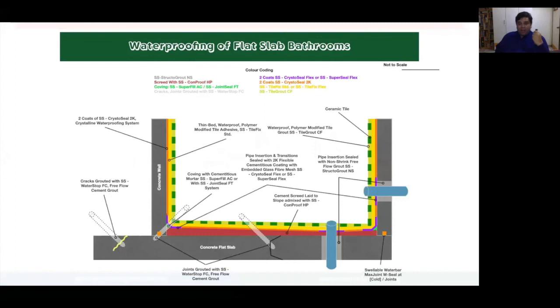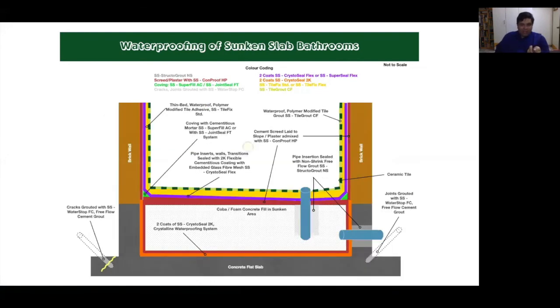So the last part that we come to, once we have taken care of the good concrete, the coating, the joints as well as the voids through injection grouting, is the detailing. I will not actually go into the details. There are about 8 or 9 different details that I have out here, like flat slab, bathroom. But you can see each one of these pretty much follows the same pattern. So what you do is first your basic concrete slab should be cast with a good integral waterproofing additive from our line.